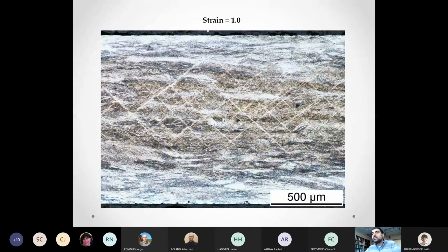And as we continue to increase the strain, so now we go to a strain of 1.0, these initial deformation bands link up into shear bands. So we have these very beautiful shear bands that run through the sample. And you can see how this is the area where we have 0.4 carbon. At the surface, we have about 0.1% carbon. And you can see how the shear bands form in the high carbon region, but they are arrested. They have to stop when they reach the low carbon region.